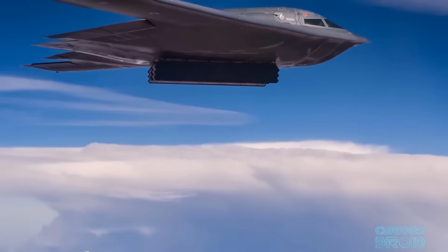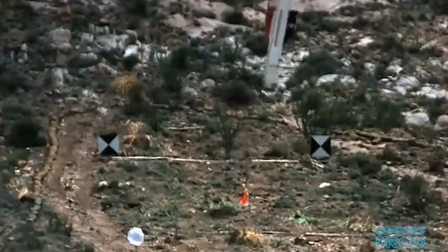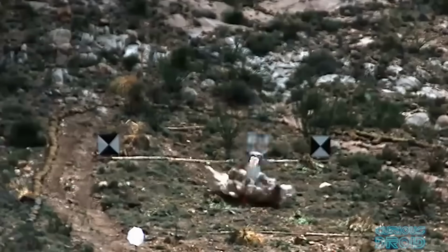But even the MOP has been upgraded now 4 times because of the threat that new, stronger types of concrete represent. While the MOP will go through 60 metres of normal 5,000 psi concrete, that drops to only 8 metres of 10,000 psi concrete, and it could be as low as 2 metres of 30,000 psi UHPC.